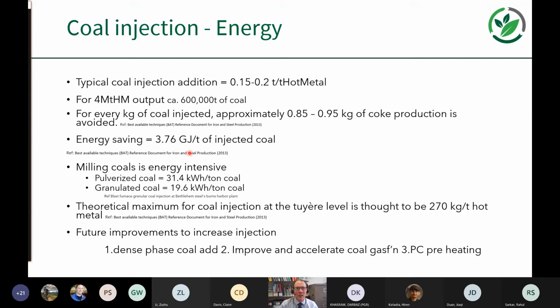Now, in the UK, Port Talbot uses granulated coal, but most worldwide coal injection is pulverized coal. That saves energy associated with its injection as well, because it requires less energy to mill that coal prior to injection into the furnace. Theoretical maximum is around 270 kilograms per ton of hot metal. So there's still some room for improving that, but in the blast furnace, you require a certain amount of coke to allow this gas permeability, to allow the blast furnace to function as a countercurrent reactor with solid materials descending and gaseous materials ascending.